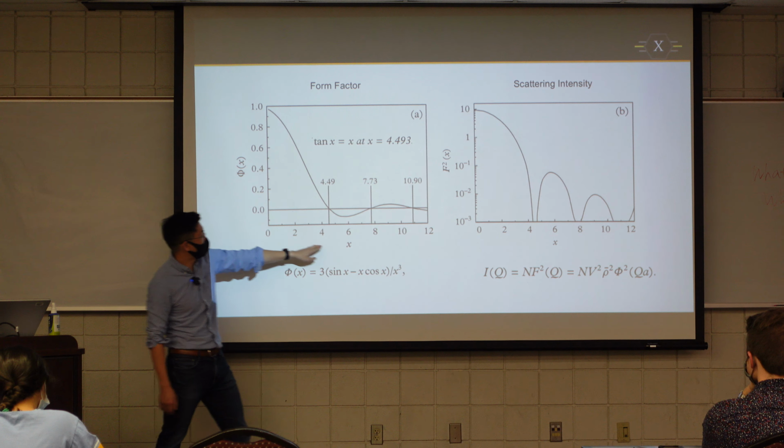And at even higher Q, we can only look at part of the individual chain. So what happens within your molecule? Even at higher Q, we are looking at segments of the molecule or inter-domain packing in the crystal lattices, etc. So that's the significance of the Q at different length scales. We are looking at different features.